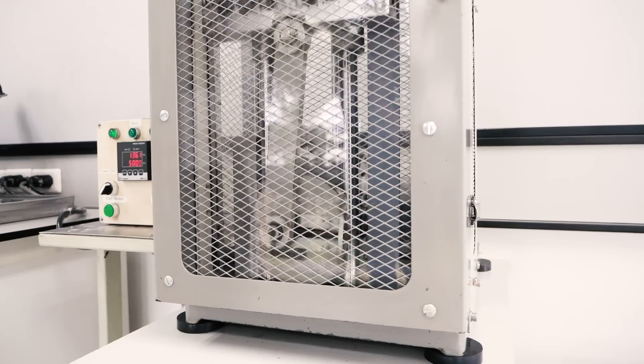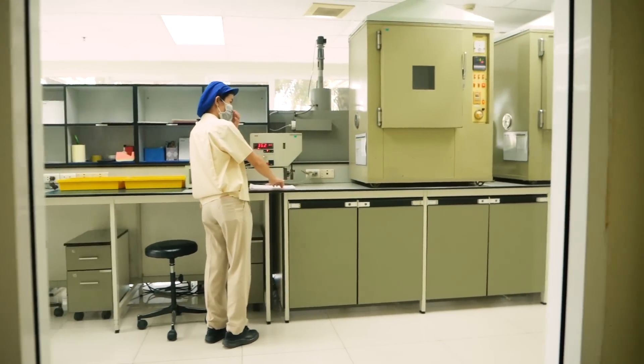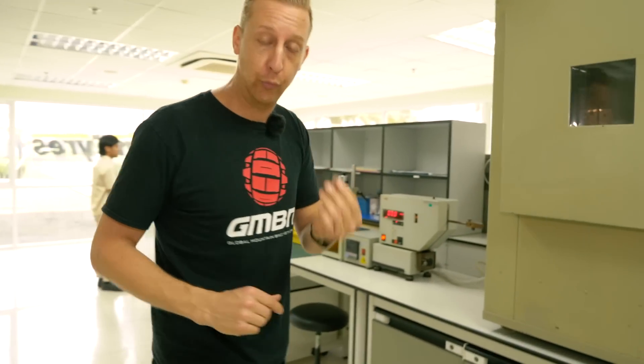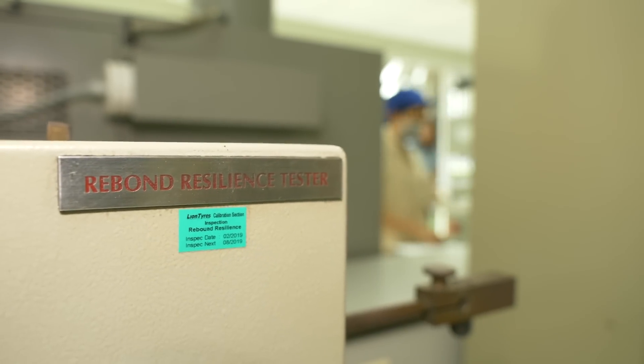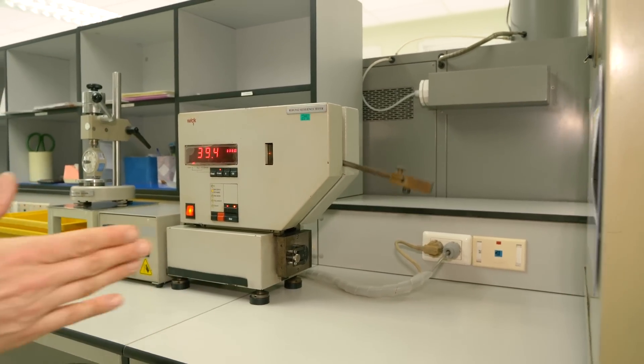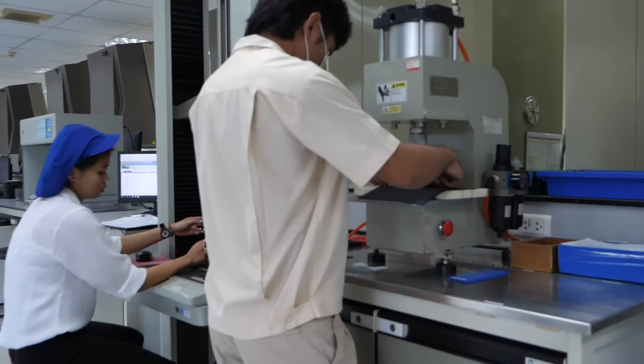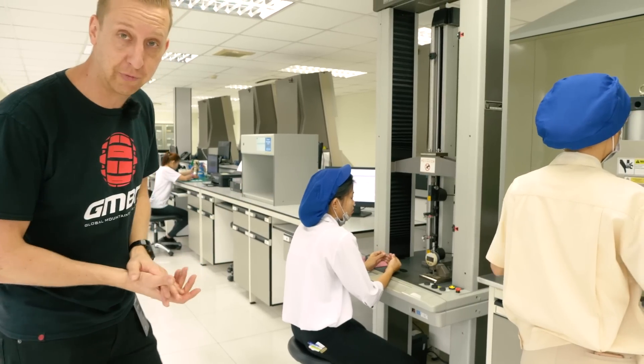Once a batch of rubber has been made, they take samples and put them through all of these processes. They get a little puck of rubber and those pucks are exposed to various different tests. Some are ozone tests, and there's a really vital one for mountain biking — it deals with the rebound of the rubber. For certain types of tires like downhill tires, you want slow rebound rubber. Using the rebound resilience tester, hitting this button, you can see the puck of rubber and it measures the speed at which the device rebounds. As well as rebound, you need to test tensile strength — measuring when the rubber can break. They load a sample onto a tension meter and measure the point at which it actually breaks, so you can test the rubber for strength and consistency.